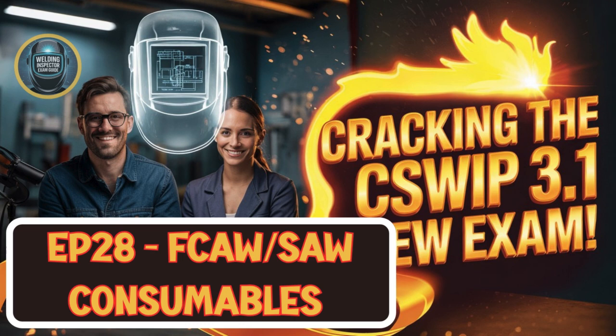Precisely. Then you have elements like manganese, molybdenum, and carbon. These are typically added to increase the hardness and strength of the final weld metal. Nickel is another common one. It's great because it improves a whole range of properties: hardness, strength, toughness, especially at low temperatures, and importantly, corrosion resistance. And finally, you often find elements like potassium and sodium compounds. These are vital for stabilizing the arc itself, making it smooth and consistent, and they also help form the necessary protective slag layer after the weld solidifies. Each ingredient has a specific purpose, carefully balanced to ensure the final weld has exactly the properties needed for its application.